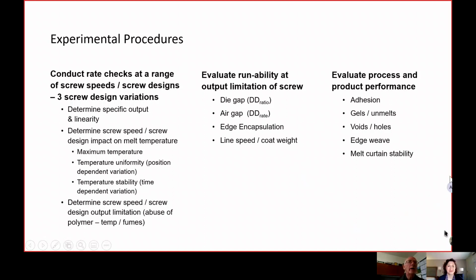So what we did in our experiment, we looked at a couple of different screw designs. We took a conventional high shear extrusion coating screw and two additional lower shear screws to see how this would impact the melt temperature and the output. Essentially, by putting lower shear energy in, we're able to get a higher output from the extruder at that low temperature, which gives us better flexibility in how we run the machine to get the speeds and quality of product.